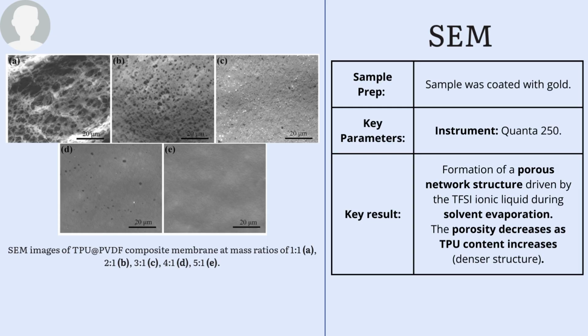Now, to verify the physical microstructure, SEM was performed. The samples were coated with gold to prevent charging and imaged using a Quanta 250 SEM. But normally, when looking for microstructure, the images are obtained with secondary electrons. The images on the left demonstrate the evolution of the microstructure as the ratio of TPU is altered.